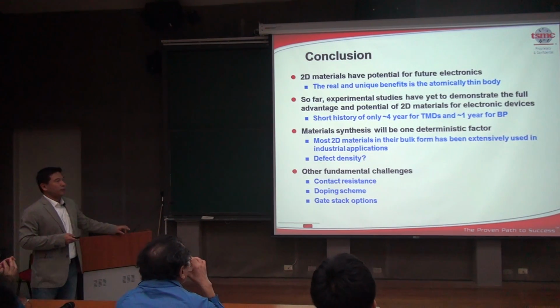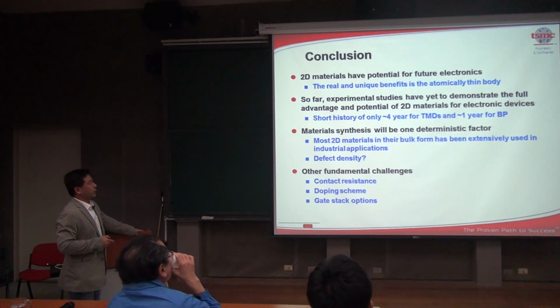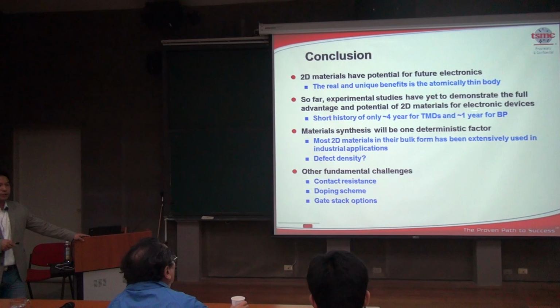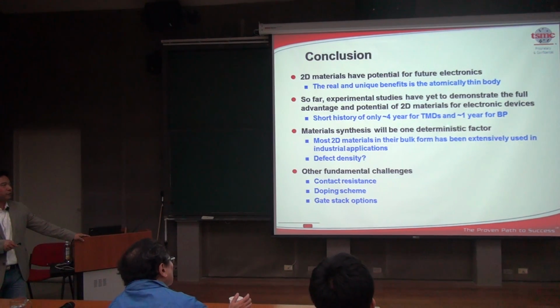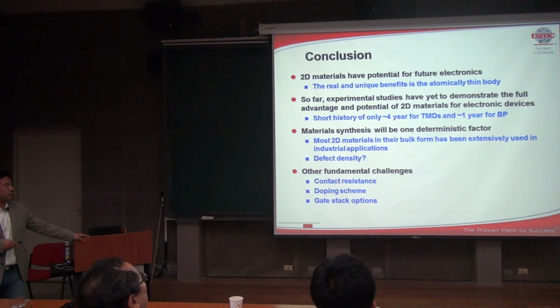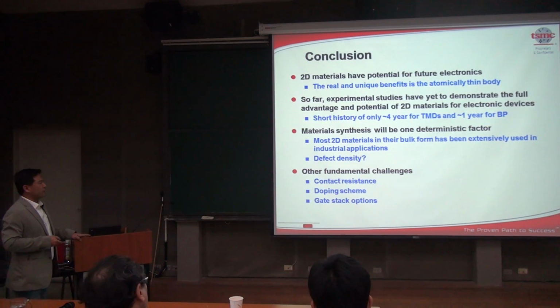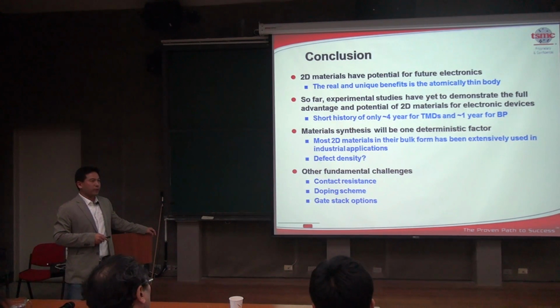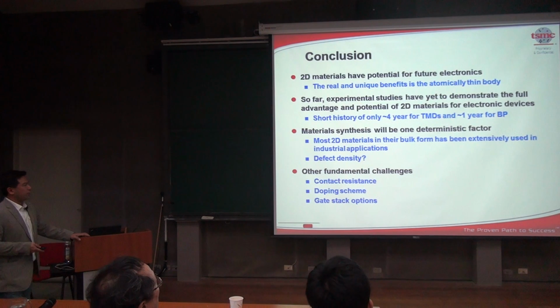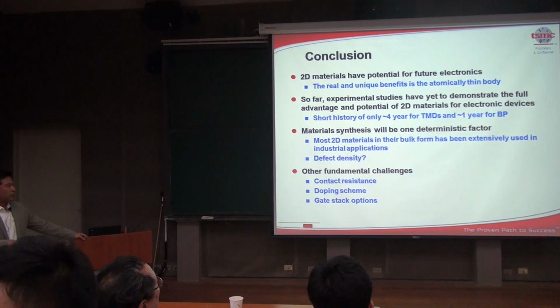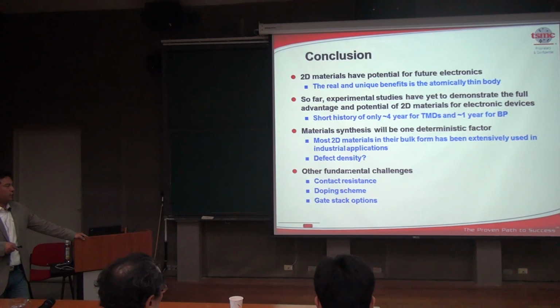So here is the conclusion of this presentation: 2D materials have potential for future electronics. The real benefit is because of the thin body. So far, we still haven't been able to demonstrate the full advantage and the potential yet, but we have to take into account the relatively short history of the TMD and black phosphorus materials. The synthesis will always be the key factor in determining whether this technology will be useful or not, and the defects in particular. If you can make very low defect materials with good control of domain size, that would be very desirable.